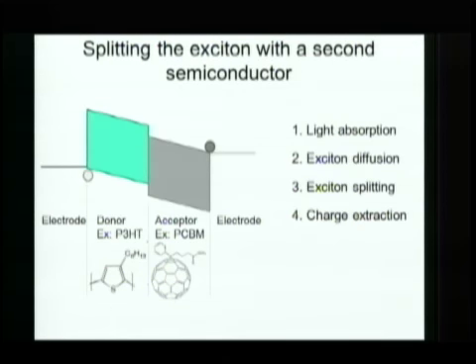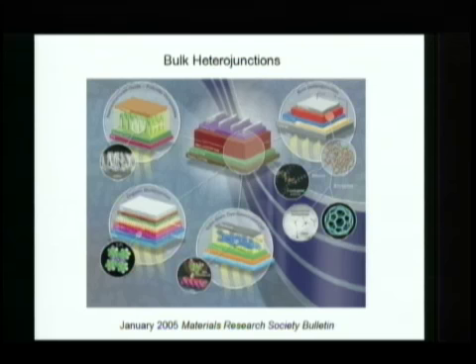The one last thing we have to do is make sure that we capture all the excitons. Turns out they only travel about 7 nanometers, and we need to make this film about 100 or 200 nanometers thick to absorb the light, so we only capture them if they're formed near the interface. But that's easy to fix. We just need to nanostructure the materials to form what we call a bulk heterojunction. A heterojunction is a junction between two semiconductors, and bulk means we have the heterojunction everywhere in the thin film.